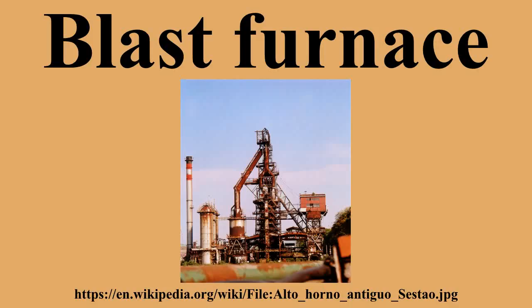Coke blast furnaces. In 1709 at Coalbrookdale in Shropshire, England, Abraham Darby began to fuel a blast furnace with coke instead of charcoal. Coke's initial advantage was its lower cost, mainly because making coke required much less labor than cutting trees and making charcoal. But using coke also overcame localized shortages of wood, especially in Britain and on the continent. Metallurgical grade coke will bear heavier weight than charcoal, allowing larger furnaces. A disadvantage is that coke contains more impurities than charcoal, with sulfur being especially detrimental to the iron's quality.